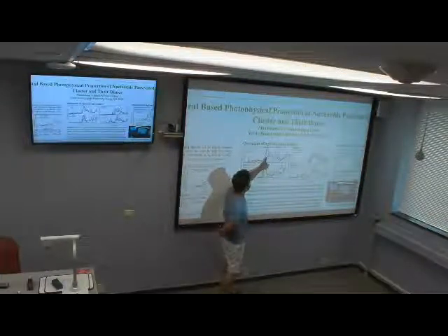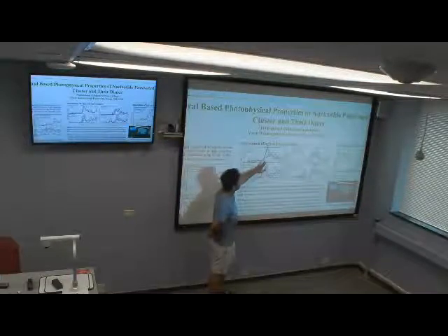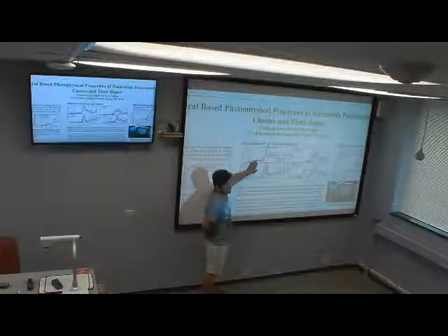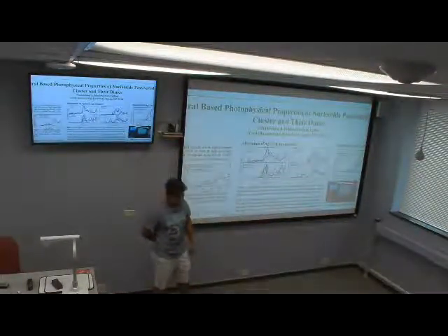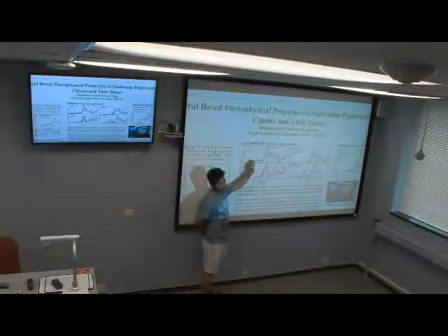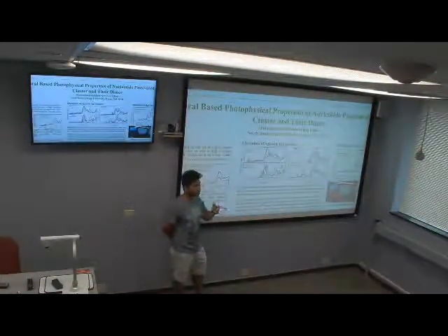The first one, if you look at the neutral one, shows that when you add 2 guanines, it increases this peak and decreases the intensity of this peak. But in the case of 5 guanines and 5 cytosines, this peak intensity is almost the same. In this low energy peak, there are a couple of peaks, 2-3 peaks. This one is the main peak. These peaks are because of doublet conformations, which are usually dark, not emissive, in this case a forbidden transition. It's also a mixture of d-d transitions with silver-to-ligand transitions. I'll show it to you later on.